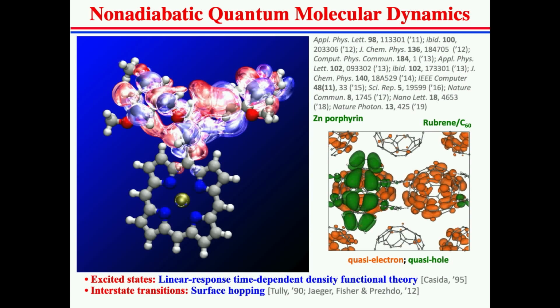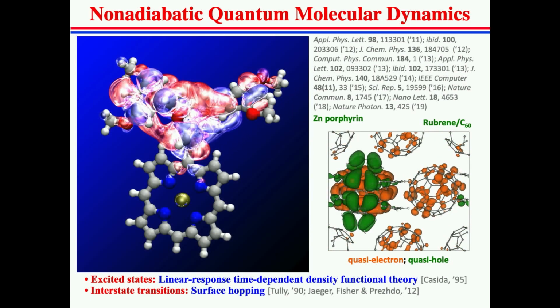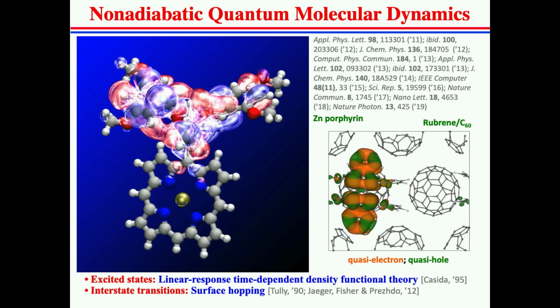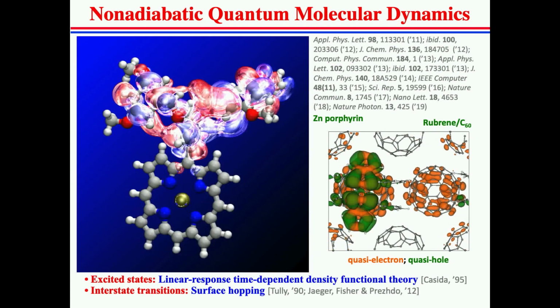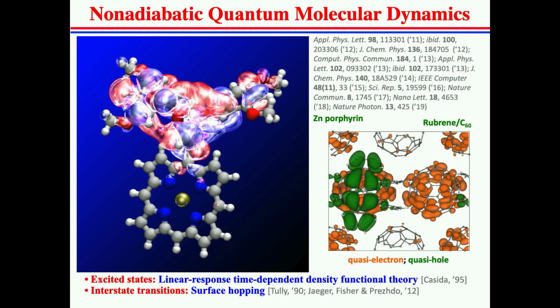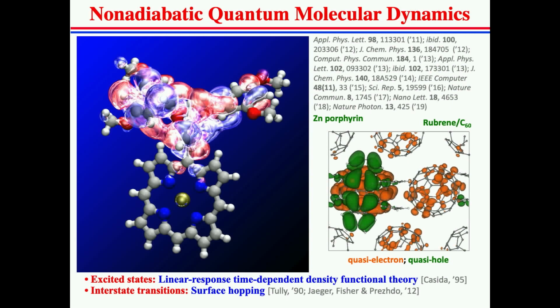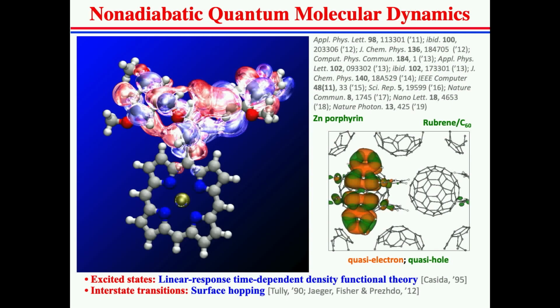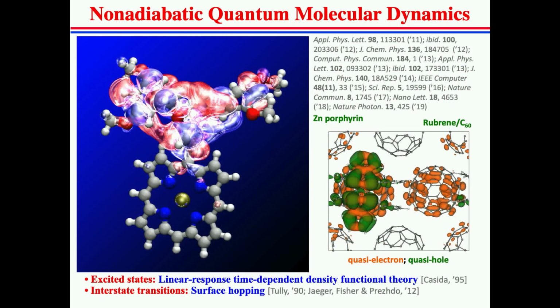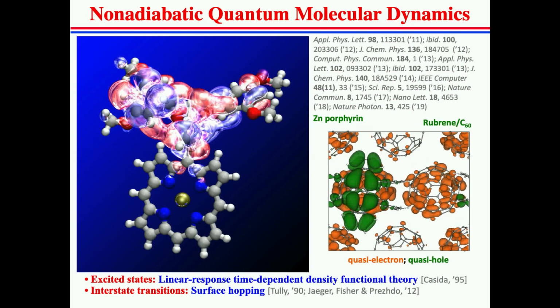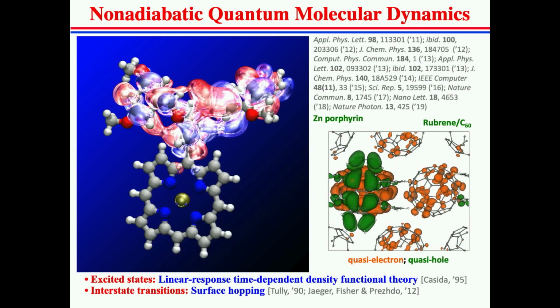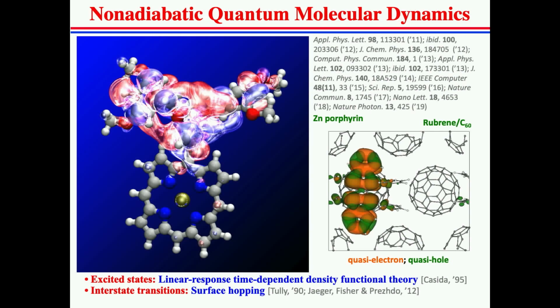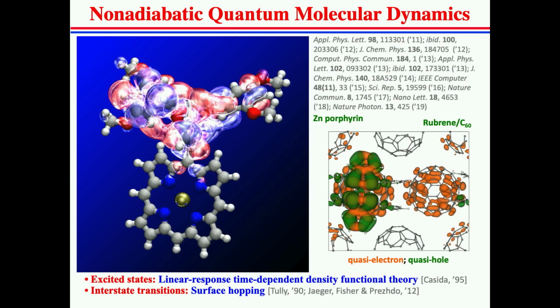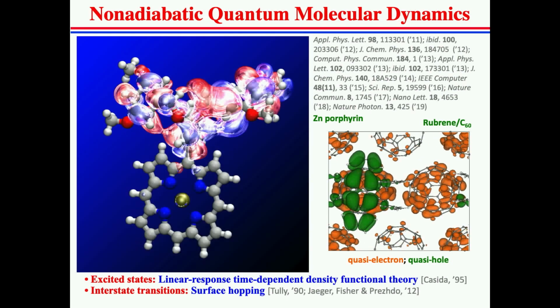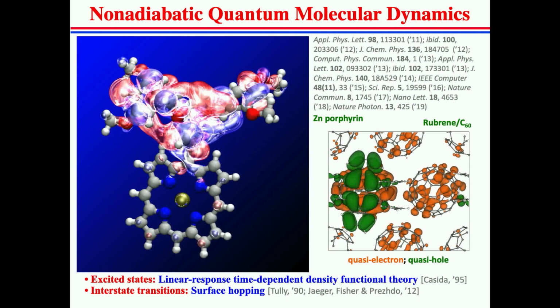This is an example of the transfer of a photo-excited electron-hole pair from the photo antenna to the so-called zinc porphyrin reaction core in a light-harvesting molecule. And this is another example: the charge separation between the quasi-electron, orange, and the quasi-hole, green, in a rubrene-carbon-60 solar cell. Those are typical applications.